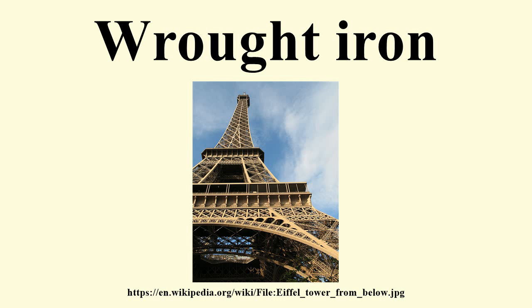Aston process. In 1925, James Aston of the United States developed a process for manufacturing wrought iron quickly and economically. It involved taking molten steel from a Bessemer converter and pouring it into cooler liquid slag. The temperature of the steel is about 1,500 degrees Celsius and the liquid slag is maintained at approximately 1,200 degrees Celsius. The molten steel contains a large amount of dissolved gases, so when the liquid steel hit the cooler surfaces of the liquid slag, the gases were liberated.